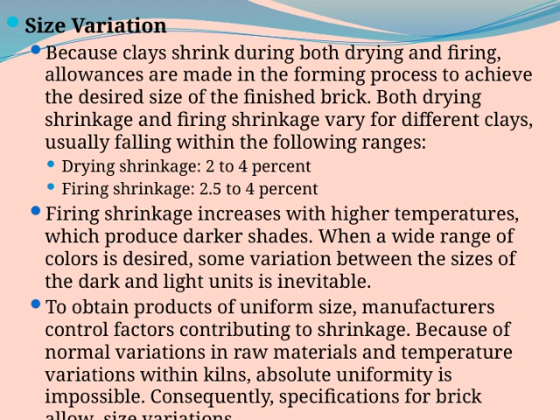It's important to note that both drying shrinkage and firing shrinkage can vary depending on the type of clay used. Typically, drying shrinkage falls between 2 and 4%, while firing shrinkage ranges from about 2.5 to 4%. An interesting point is that firing shrinkage increases as the firing temperature gets higher, which also results in darker shades of bricks. So, if a manufacturer wants a variety of colors, some size variation between dark and light bricks is inevitable. To achieve uniformity, manufacturers carefully control factors like moisture content and firing temperature.